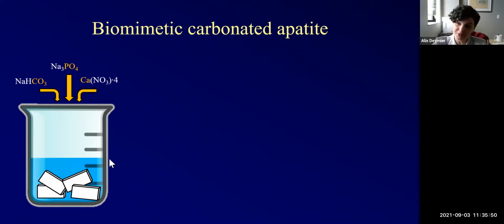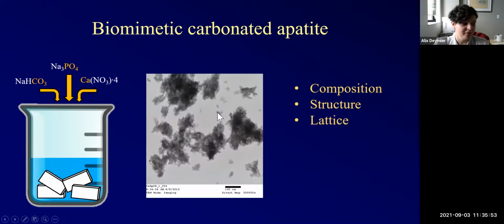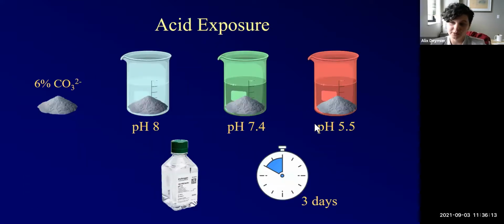you can actually precipitate crystals that are nanocrystals with composition, structure, and atomic lattice that looks almost identical to what you have in bone. So we can replicate bone crystals in the lab. We do this all the time. So we went ahead and we did this, and we made biomimetic crystals that had about 6% carbonate. That's what we see in bone. It recapitulates the right type of size, so we're good to go.